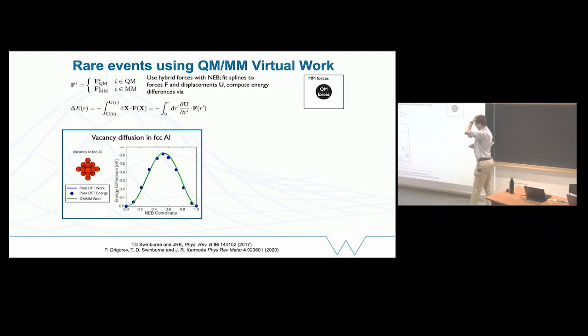So we can look at a direct energy calculation in comparison to what we get using only a very, very small quantum region centered on a moving vacancy in aluminium, and we get a good agreement. So we can compute barriers. That means we can feed in to kinetic Monte Carlo or larger scale models in this way.